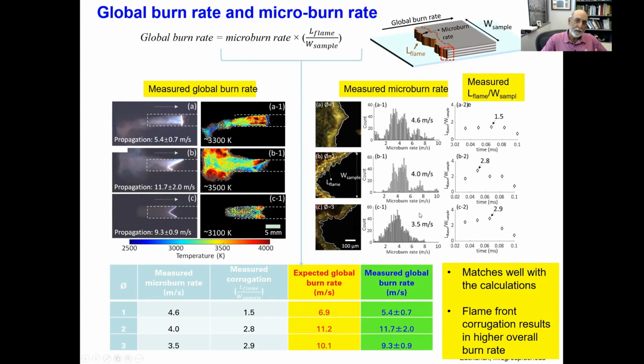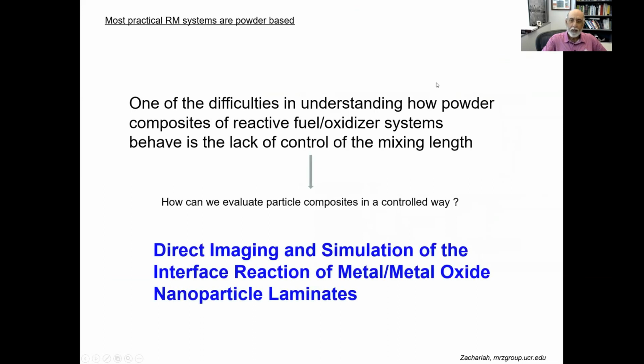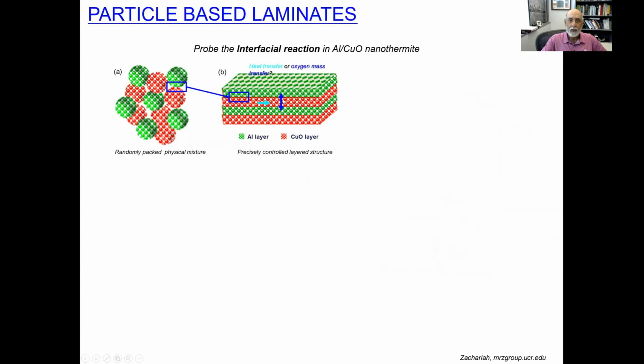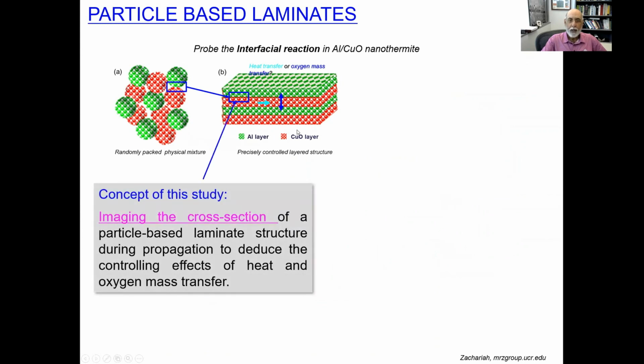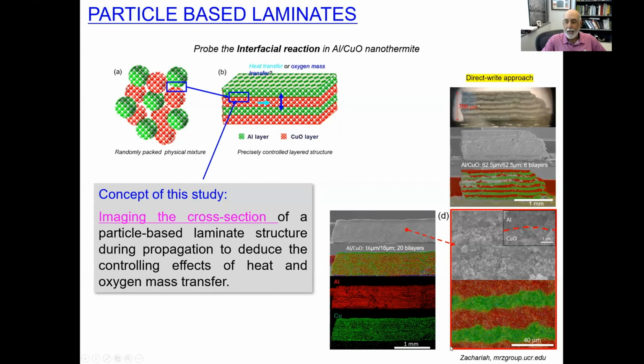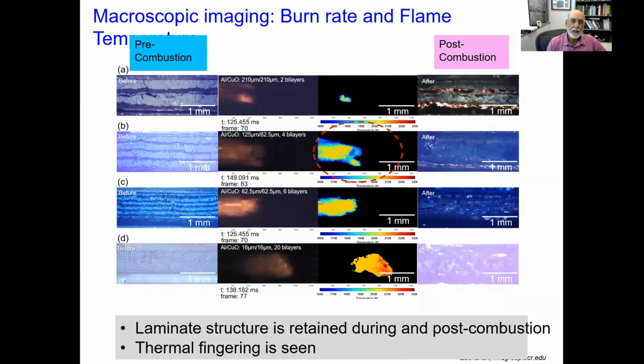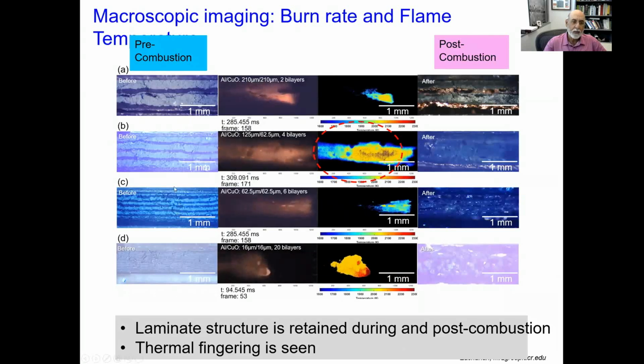And this was of course for these very nice laminated structures. We've also looked at more practical systems by directly looking at the interface reaction in nanoparticle laminates. So the same idea, but now we're going to look at laminated structures of fuel and oxidizer, but made of particles. We're going to make layered particle structures, and we're going to interrogate this interface. So these are the layered structures that we've made. The colors denote whether it's a fuel or an oxidizer. These are aluminum copper oxide, but remember they're particles now. They're layered particle layers. And so this is what these interfaces look like as a function of the spacing between the layers.